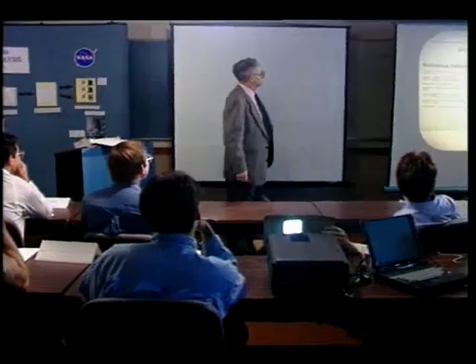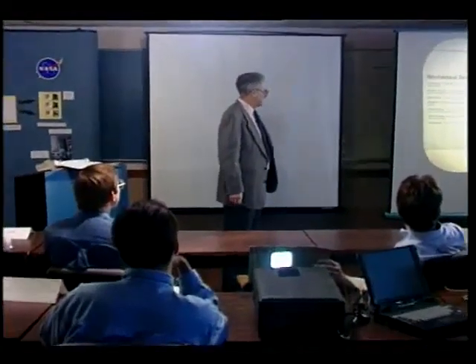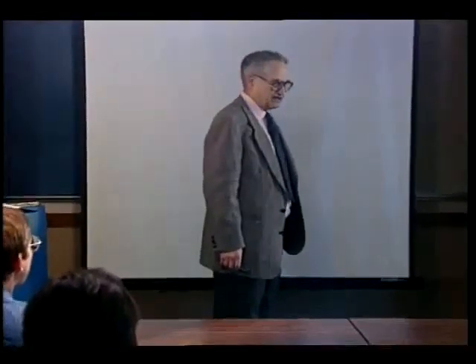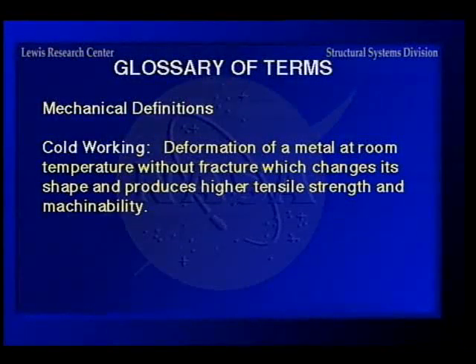The plain carbon steels, you can cold work them during deformation. In fact, one of the reasons that they start out with the so-called wire, if you will, now wire, somehow 3/4 inch wire doesn't strike me as being wire, but that's what they call it in the fastener plants. They run it through an annealing furnace to get it as soft as possible before they start. And so the fasteners are actually formed out of this annealed wire, and they are cold worked during the forming.